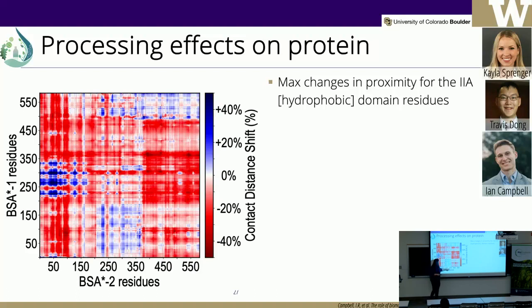There is this block of residues, the IIA residues that are between 250 and 350. They correspond to the hydrophobic domains, and they are the ones that are pushed further apart. Everything else comes closer together as you hot press the material.